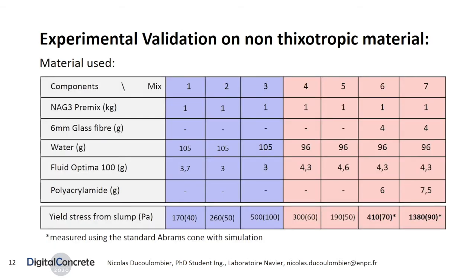The mortar used for validation and also for additive fabrication in building facilities is formulated using a premix provided by Lafarge-Holcim. However, to strongly reduce thixotropic behavior, no accelerator is introduced in the mixture. Then, the different yield stress values are obtained by modifying water and superplasticizer contents, or by replacing the accelerator by a flocculant additive, the polyacrylamide. The blue experiments were conducted using the specific extrusion device and a simple manual protocol, while the red ones were conducted using an automatic protocol installed in the building facilities. Let us now present both protocols.